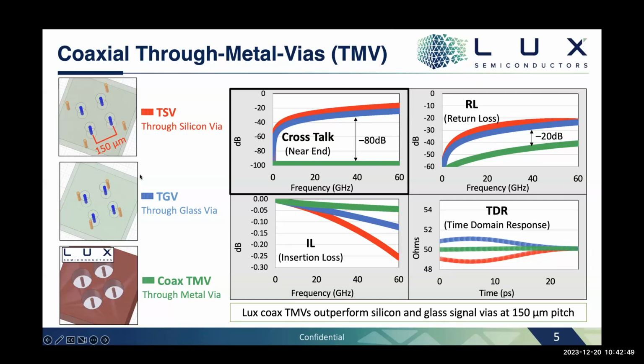They'll basically drill a hole through the substrate, fill it with copper, and place these pins. They'll place ground pins next to signal pins in an attempt to reduce crosstalk, create 50 ohm impedance, etc. And so, although the diameter of, say, a TSV would be smaller than what we can achieve with a metal signal pin, oftentimes if you really care about crosstalk, you'll have ground pins circling the single signal pin. Right. And so what ends up mattering is the signal to signal via pitch. And you automatically get that with the coaxial TMV, because it leaves this ground metal around it. So it eliminates crosstalk entirely.